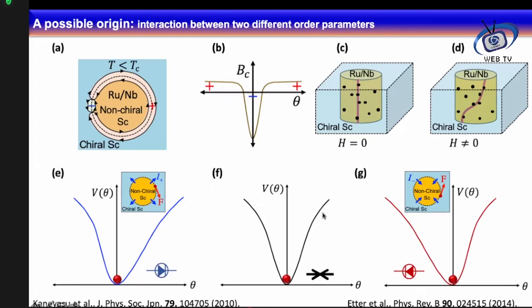The pinning potential of this vortex can be symmetric. If it is symmetric, then your applied current would not change it. It will not move it in either direction, because in both directions there is a very large potential that it has to cross. But if somehow toward the positive direction the pinning potential has been perturbed, then our applied current will apply the Lorentz force on this vortex and move it towards one particular direction. And if the perturbation in the pinning potential is the other way around, then the Lorentz force will also be the other way around for the other direction of the current.